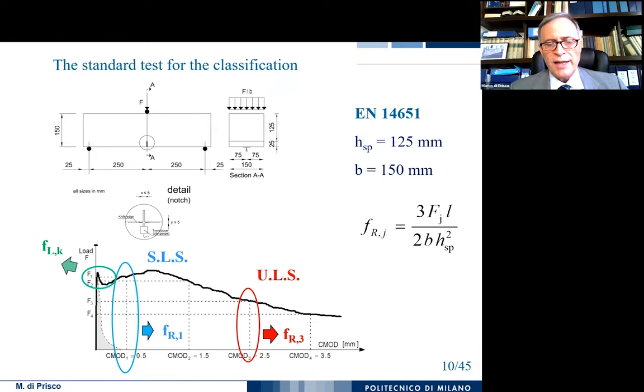and this behavior grows with the increase of the redundancy of the structure. In order to characterize this material, after a long discussion in different committees, it was decided that the best would be just to have a three-point bending test on a notched cross-section. And here you see the sides. It's essentially a square section of 150 millimeters per side, and we have a notch of 25 millimeters in the center.